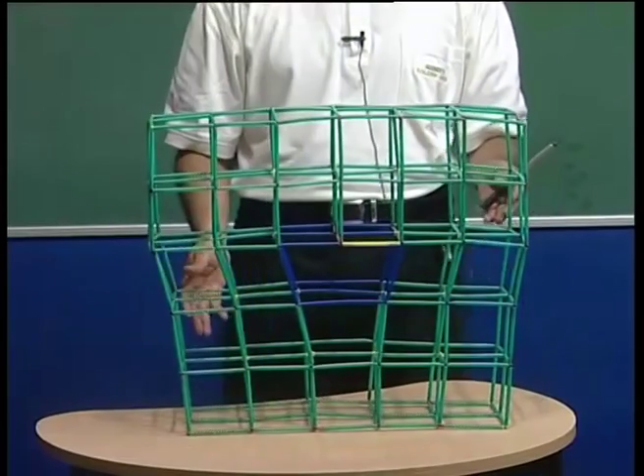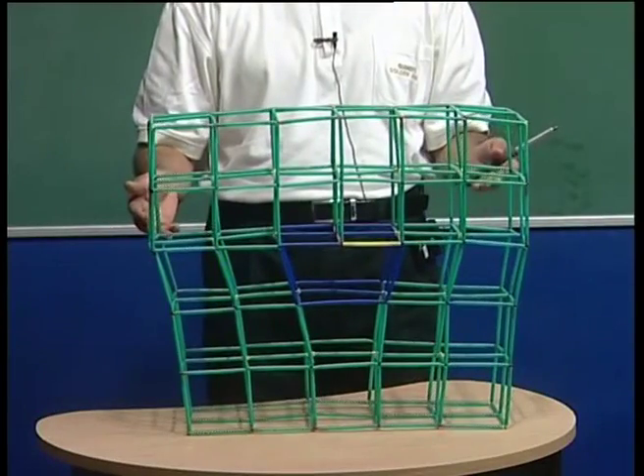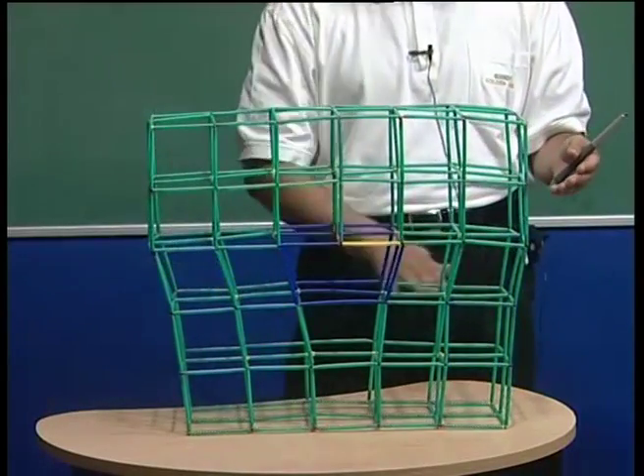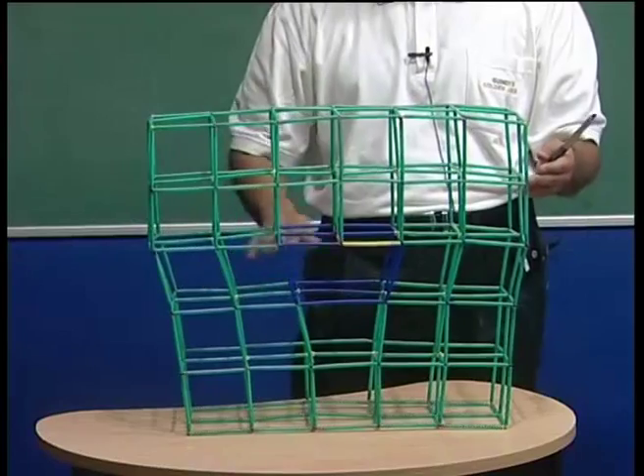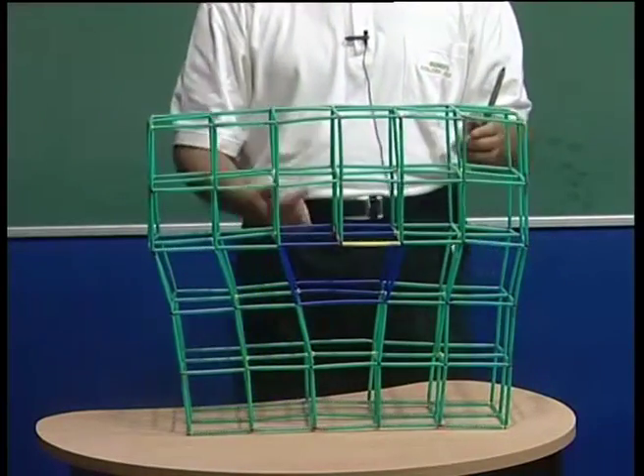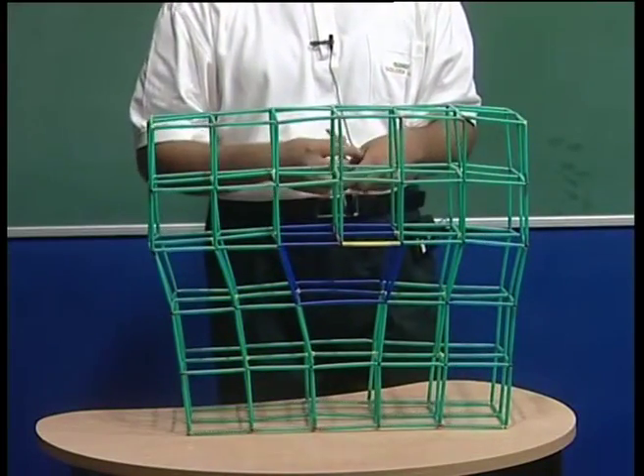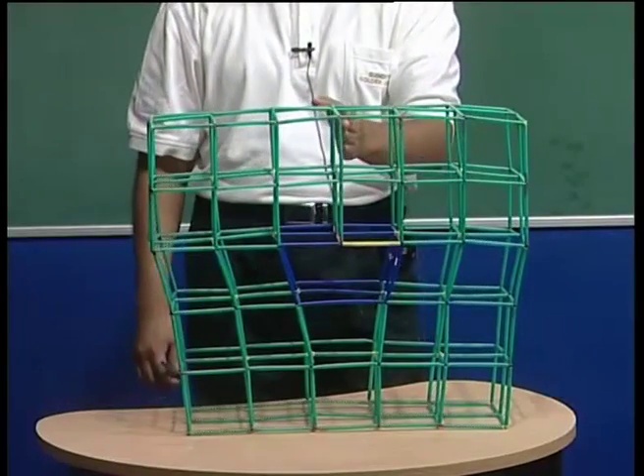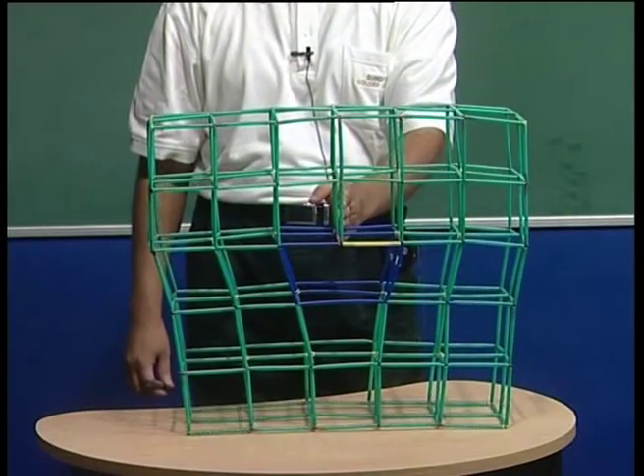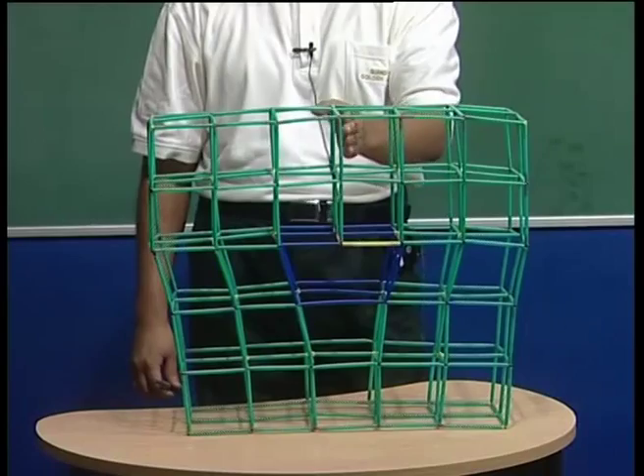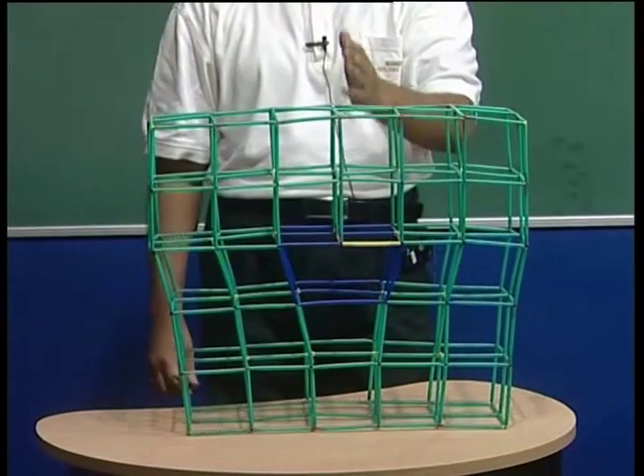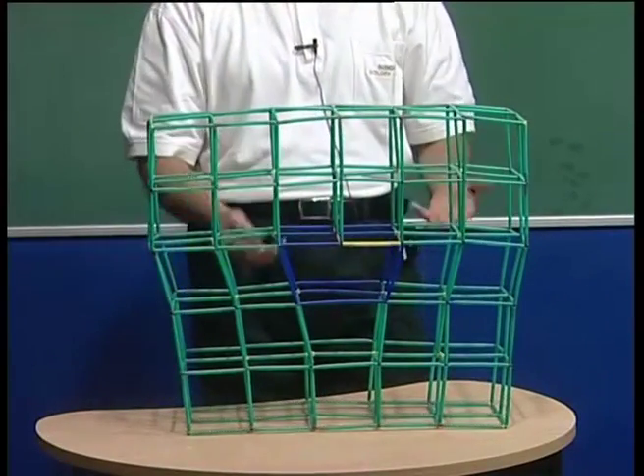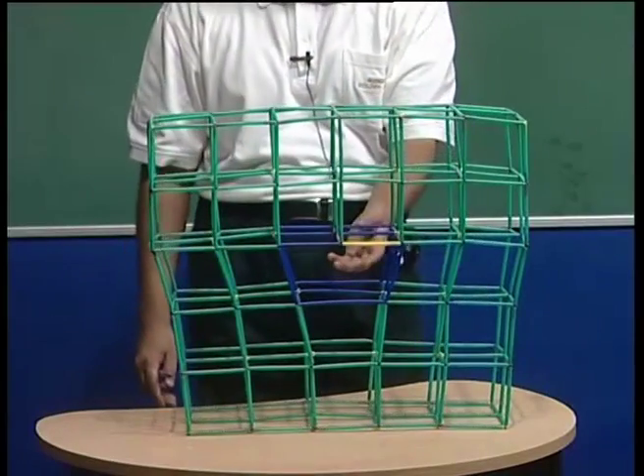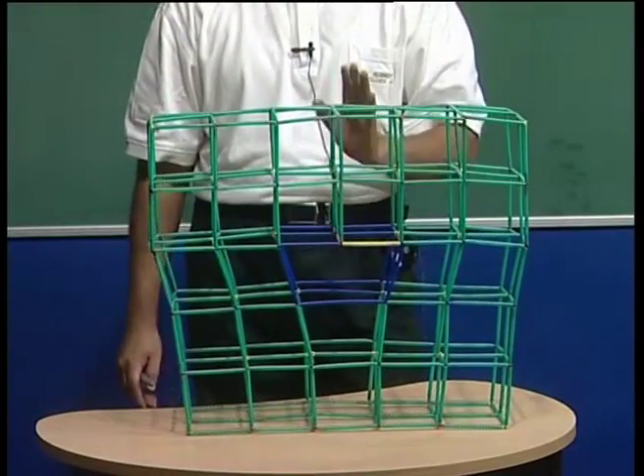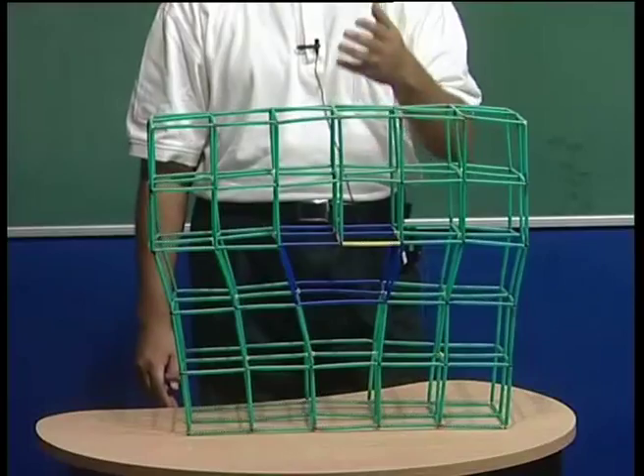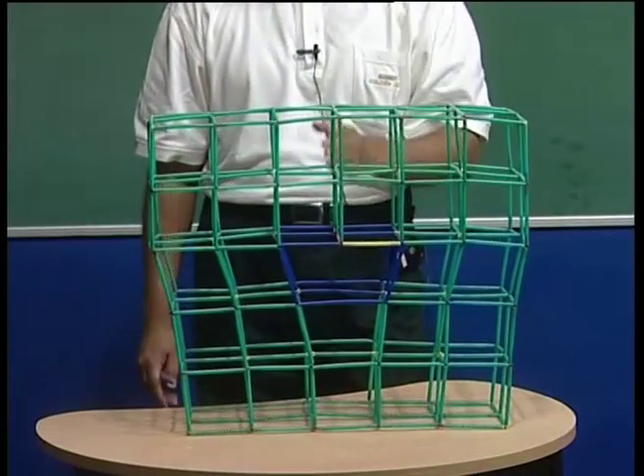And as we shall see by taking examples from face centered cubic crystals, etc., typically this would be a close pack plane in these kinds of close pack crystals. Okay. So what are the things associated with the dislocation now? Let me revise. This edge dislocation is associated with an extra half plane. Of course, this extra half plane need not really be half, it could end somewhere in the crystal. Only thing, it should not go all the way through the crystal, otherwise it will make it a perfect crystal. So it has some end somewhere within the crystal, and though we use the word half, we mean it does not go all the way through. So that is the first thing.